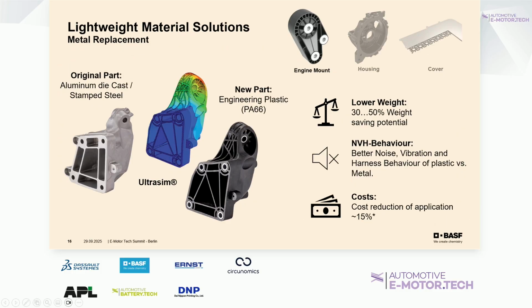The next topic is more about, as I mentioned, metal replacement. So I would say we have a strong background in so-called engine mounts for the typical internal combustion engine, so the fixation from the engine to the chassis. In the past this was quite often done out of aluminium die cast or stamped steel. And we developed, together with our partners for sure, some solutions out of PA66 or PA6. The main target is for sure weight reduction, so up to 30 to 50%, depending on the initial design. Also better NVH behavior, as well as, I would say at the moment the most important point, the cost reduction. So also up to 15% cost reduction.